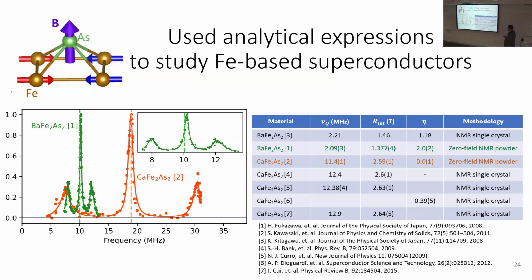These black lines, extracted from the literature, differ in that they have a single crystal, but they also did high field NMR with an externally applied magnetic field. When you do that, you cannot just extract everything directly. The combined Hamiltonian I gave earlier, the Zeeman Hamiltonian plus the quadrupolar Hamiltonian, assumes that the internal magnetic field is aligned with one of the EFG principal axes.